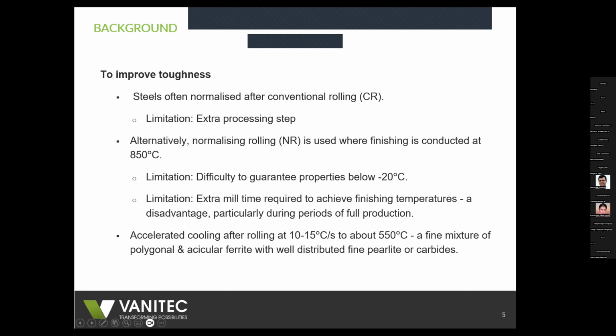Okay, sorry, I just missed the first step. You either have to normalize the material, or you would have to normalize roll the material. So both of those are extra steps and uneconomical. The other alternative is to apply accelerated cooling after rolling in the region of 10 to 15 Celsius per second to an interrupt temperature of about 550, where you get a fine mixture of polygonal and acicular ferrite and a good distribution of pearlite and carbides. But the accelerated cooling demands even cooling. You can easily mess up shape if you don't do it properly.